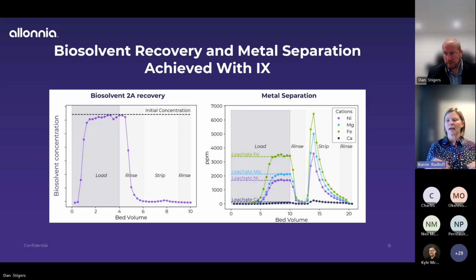And the IX column is able to remove all of the impurities. It's capturing the nickel, the magnesium, as well as the iron. And then we're able to recover those elements in the strip step. In this case, we're using a strong acid IX column, so we're able to use sulfuric acid to strip those metals out.